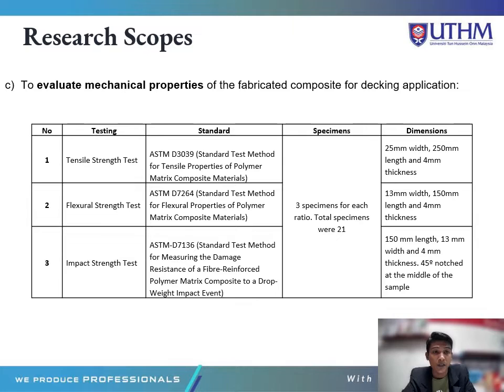The third research scope is to evaluate the mechanical properties of the fabricated composite for decking application. For mechanical properties, there will be 3 types of tests. The first is the tensile strength test using ASTM D3039. The second is the flexural strength test using ASTM D7264. And the third is the impact strength test using ASTM D7136. There will be 3 specimens for each ratio for these tests, a total of 21. The tensile strength test specimen will be 25 mm width, 250 mm length, and 4 mm thickness. For the flexural strength test, 13 mm width, 150 mm length, and 4 mm thickness. For the impact strength test, 150 mm length, 13 mm width, and 4 mm thickness with a 45-degree notch at the middle of the samples.